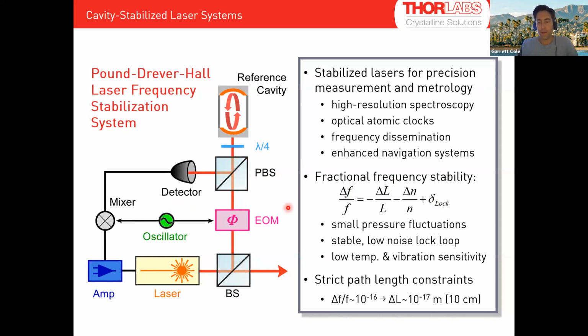If I use ULE, which has zero expansion, and I control the temperature, I can get rid of gross fluctuations of the cavity length. And if I put the thing in a vacuum chamber, I can take away any index perturbations in the cavity. And ideally, I build this system up from the ground up with low noise electronics. So I'm ultimately limited by the microscopic length fluctuations, which again is this Brownian noise issue that I showed earlier.